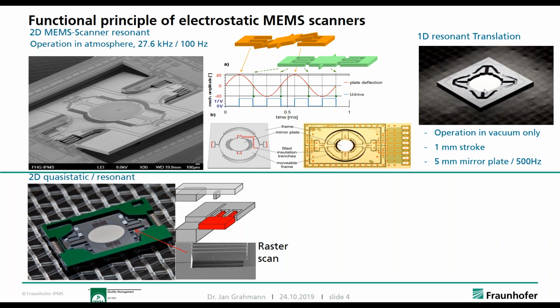Here on the right side, you see another example for the options of that technology. So we cannot just have mirrors that rotate around 1 or 2 axes. We can also have a translational movement. So that's a 5 millimeter mirror that moves up and down. In this case, we can only do that in vacuum because the air damping is much higher than with a torsional oscillating scanner. And that specific mirror can do a stroke of plus minus 500 microns, so a complete stroke up to 1 millimeter, and is driven at 500 hertz. So those are possibilities for the resonant scanner technology.